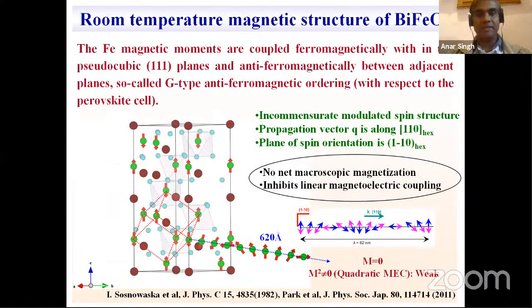And this is the magnetic structure of bismuth ferrite, in which the magnetic moments of iron, which is the only magnetic ion here, are ferromagnetically coupled in the 111 pseudo-cubic direction, and antiferromagnetically coupled between adjacent 111 planes. So basically in bismuth ferrite, Fe spins construct a G-type antiferromagnetic ordering. Here a G-type antiferromagnetic ordering is shown, in which the Fe spins are also incommensurately modulated with a periodicity of 620 angstrom.